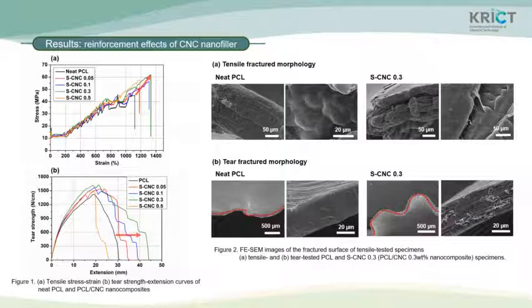The remarkable grain structures on the relatively smooth fracture surface of PCL reveal that cracks propagate along crystal grain boundaries during deformation. Meanwhile, PCL-CNC nanocomposite exhibited an uneven and rough fractured surface accompanied by crazing phenomenon. The evolution of microfibrils through crazing promotes ductile deformation because they act as bridges that absorb external stress. As a result, crack propagation and fracturing are delayed during the tensile testing of the nanocomposite.